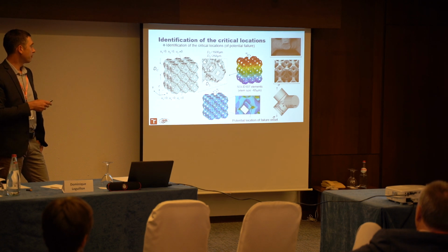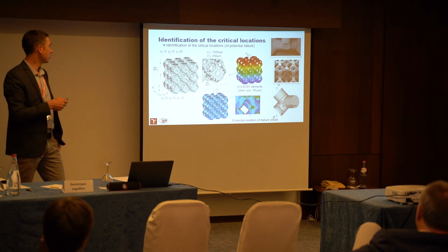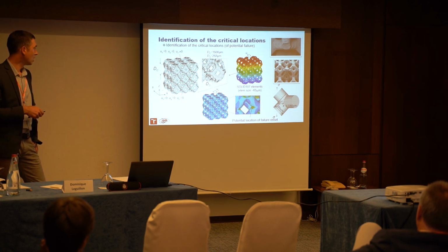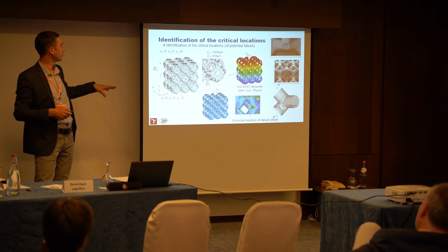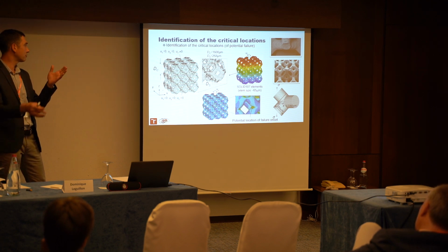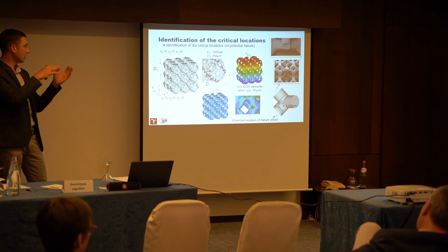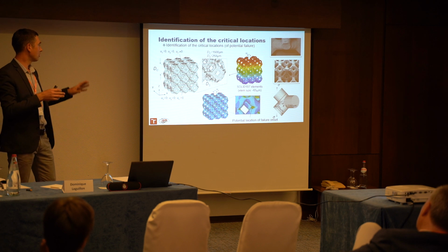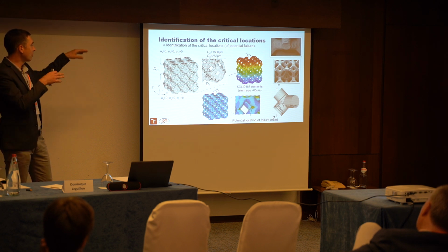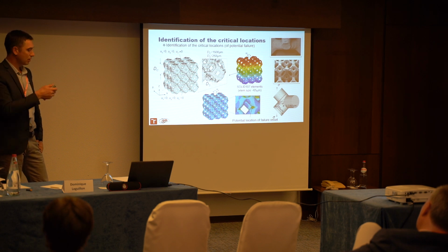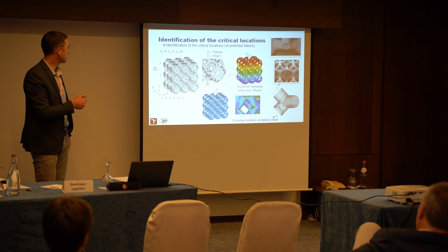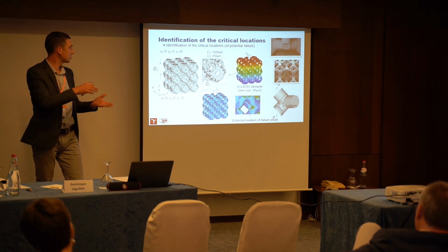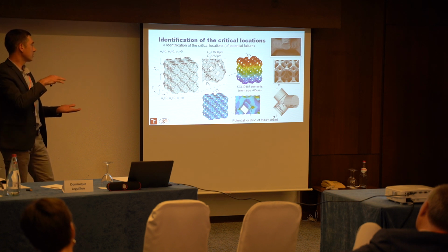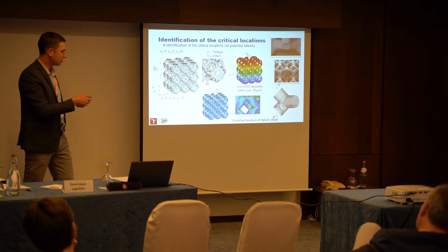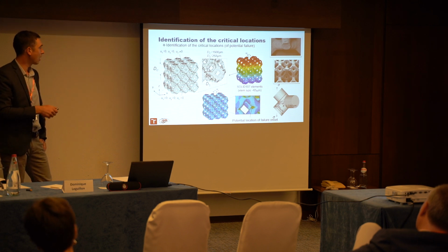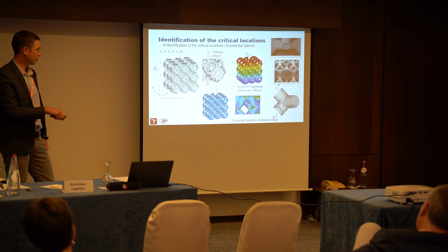So now how can we apply the coupled criterion to predict the failure of the whole foam structure. Of course, we have many fracture surfaces because there are many struts, and to break the foam and to determine the strength, you have to break really a lot of struts. So it's not possible to have a realistic crack in all positions or potential locations. So we try to find another way. So we selected just one location of strut-strut connection. Since everything is symmetric, loading is symmetric, geometry, then we can expect that at all locations under certain deformation we will have very similar conditions.